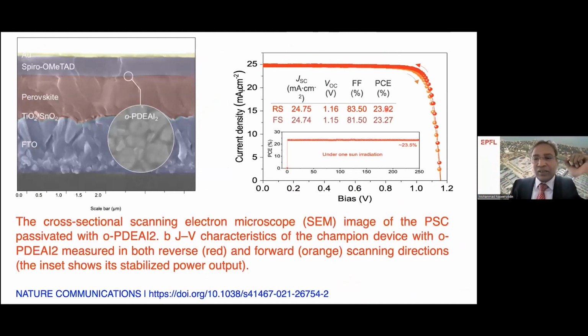So here is the best cell efficiency which I am reporting. That's 23.92 in reverse scanning, and 23.27 in forward scanning, with a small hysteresis. And this is maximum power point tracking over 250 hours. The efficiency remains quite constant. And the cross-sectional image is shown here. As I mentioned before, this is a conducting glass, and then we have a compact layer followed by the TiO2, tin oxide, perovskite, a very thin layer of this cation deposited on top of the perovskite, spiro-OMeTAD, and gold as